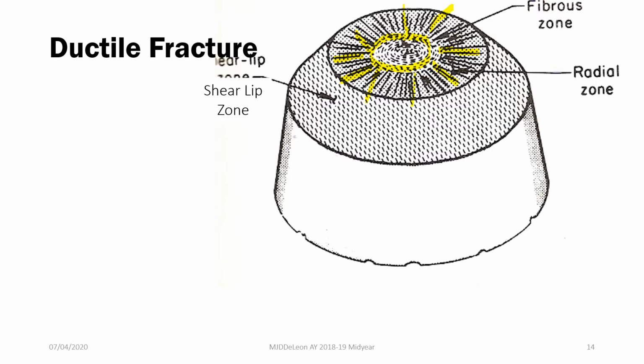So mula dito sa figure na to, we can see that our crack started from the center because the location or the center of the fibrous zone, this essentially tells us where the crack originated. Then magpropagate siya to the radial zone, and once mawalan na ng ability yung material mo na ma-hold pa yung structure niya or ma-hold yung stress, magkakaroon siya ng catastrophic failure in which makita natin, makakaracterize ng shear lip zone mo.